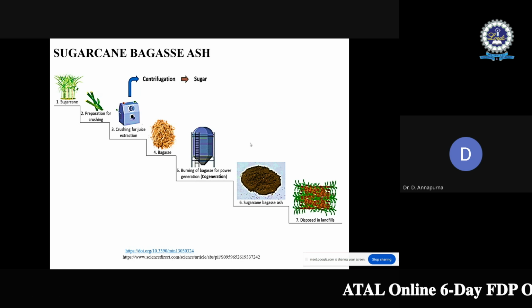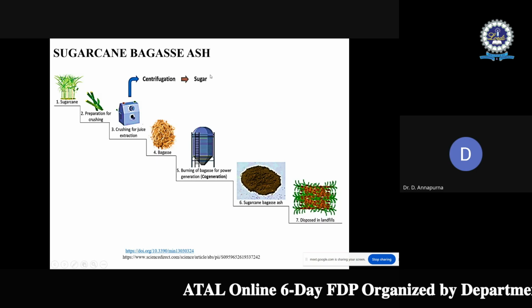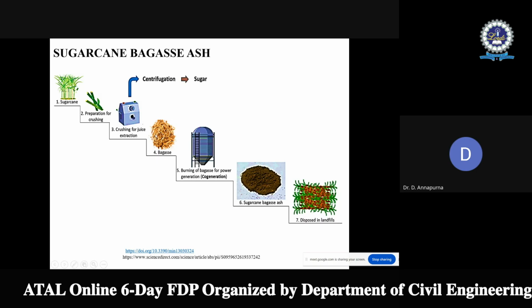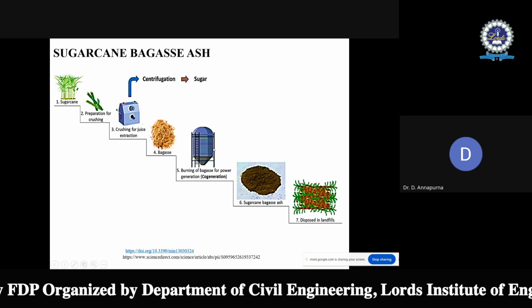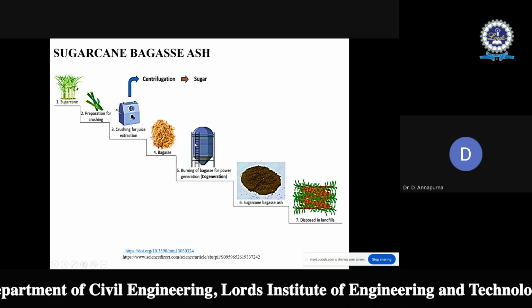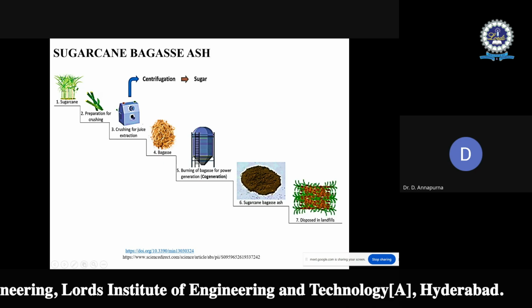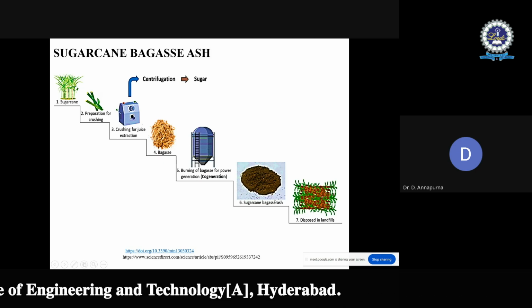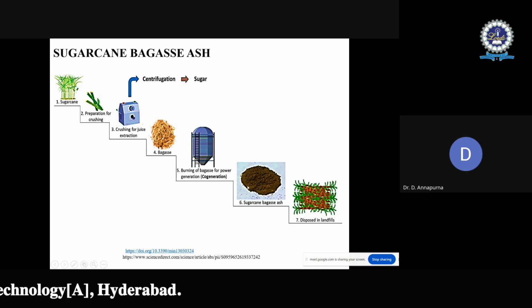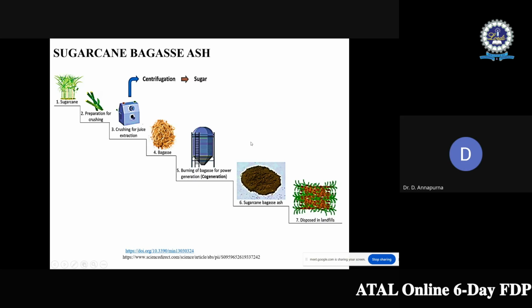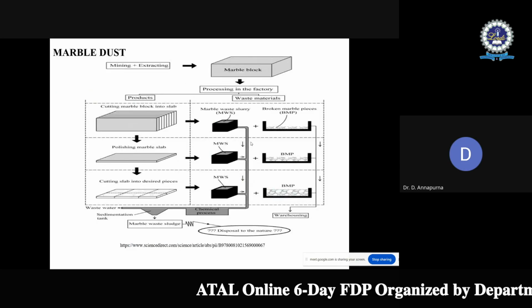So from the sugarcane industries, when the bagasse is produced, that bagasse will be burned to get a fine powdered form. That will be called sugarcane bagasse ash. It is rich in silica and alumina content, so it can be used as source material in the production of geopolymer concrete. Then comes the marble dust.